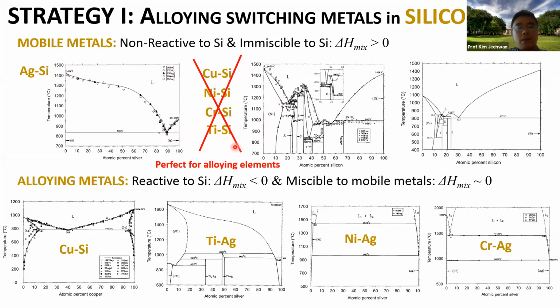However, this line compound material is perfect for the alloying metals. The reason is that silver forms a very weak interface with the silicon, so it can freely move around. That is becoming the source of the problem of having non-uniform switching. So we can add a little bit of these compound-forming metals to form some sort of bridge between the unstable silver and silicon interface. These silicide metals form a very stable interface with the silicon. So alloying metals was a candidate. It has to be reactive to silicon.